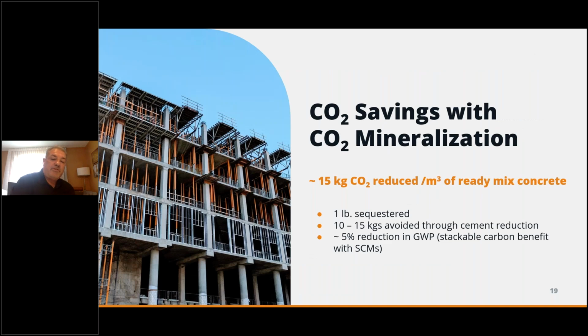So typically what we'll see on a cubic meter of concrete is that we'll reduce the environmental impact through cement reduction by 10 to 15 kilos of CO2. This is important because when we start looking at the global warming potential of a project, it starts to add up pretty substantially. If you have a larger project that might have 20, 30, 40,000 cubic meters of concrete, you can imagine the reduction starts getting into the hundreds of thousands of tons of CO2. And that's what we're trying to do, sequester that CO2 permanently in the structure through using our technology. So that's an example of what we see.